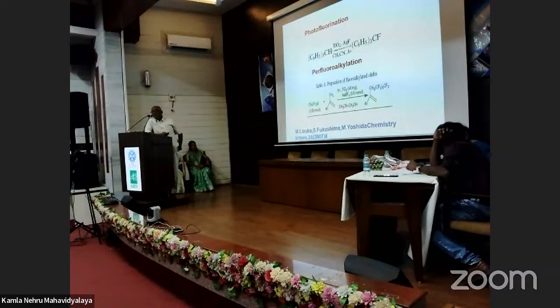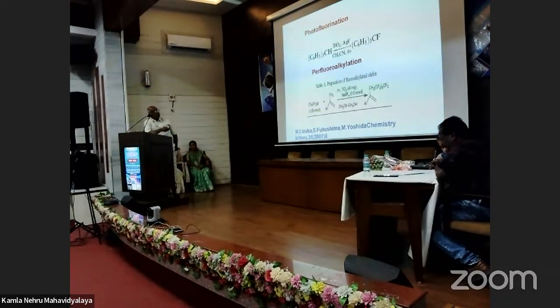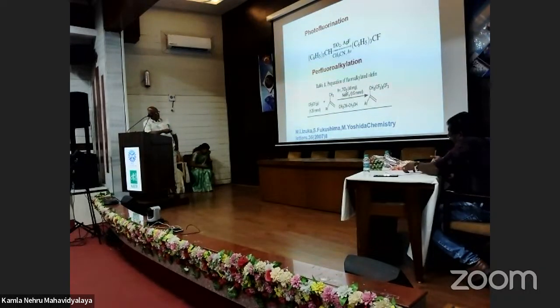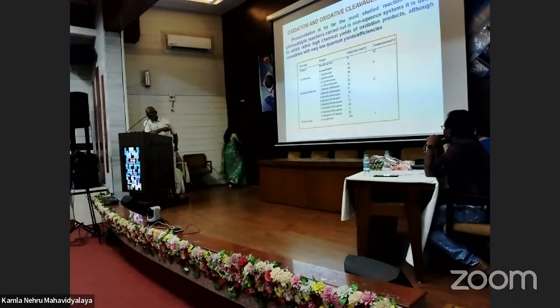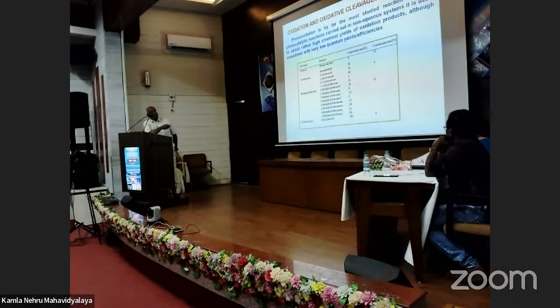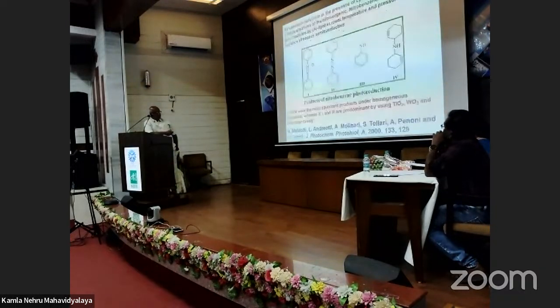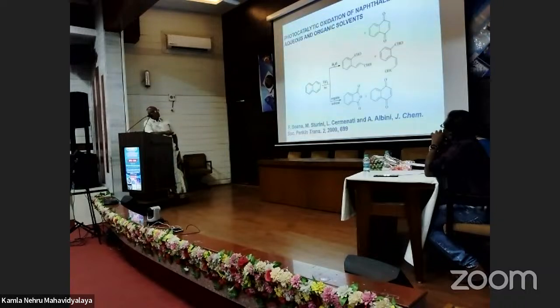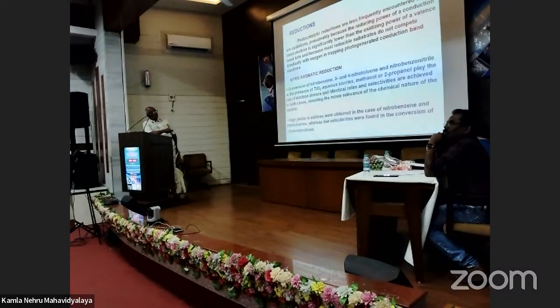And similarly, TiO2 can be used for fluorination. In the presence of silver fluoride and TiO2, you can fluorinate that compound. So you can see fluorination or fluoroalkylations. And similarly, the oxidation reactions. You can see toluene can be oxidized to benzyl alcohol, and alkanes can be oxidized to alcohols. These are some of the reactions. This is again the oxidation of naphthalene in aqueous and organic solvents. In the presence of TiO2 and light, you can get these different kinds of products.